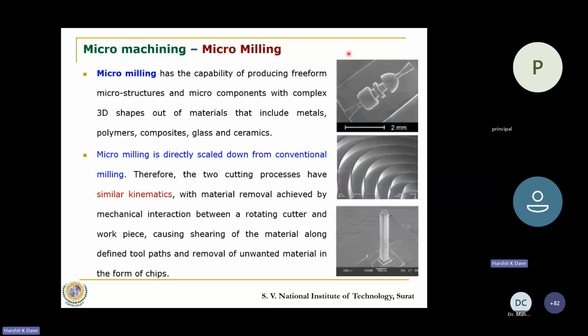The other process which I said, which is widely used, is micro milling. You can just see this part. Here it shows that 2 mm is the width. So this entire feature may be somewhere around 2 to 3 mm. So in spite of this part having dimensions in 2 or 3 mm, the features that are being generated are into micro domain. Because of that, we observe that this can be termed as micro milling. Two of these features would be in micro domain.